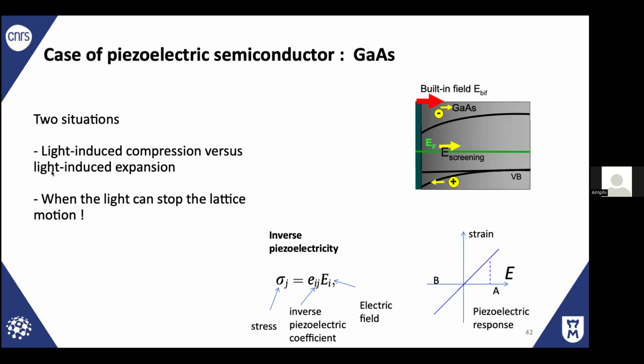First, about the piezoelectric semiconductor. I will show you that with light, we can induce compression or expansion. We can even stop the lattice motion with light. I will show you this just by playing with the competition between two kinds of electron-hole acoustic phonons, which are deformation potential and piezoelectric effect. First of all, I discuss that situation. We have a semiconductor, which is p-doped in that case, and there is a built-in field at the surface. Basically, majority carriers are trapped, and there is a built-in field present on the surface.